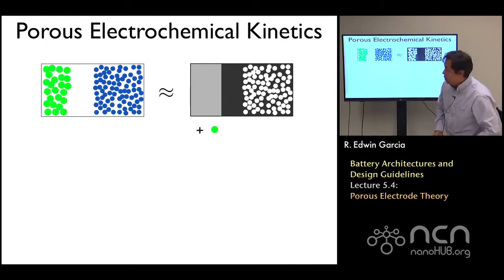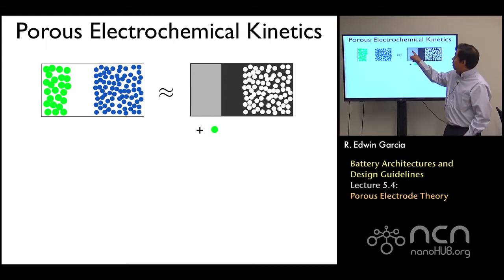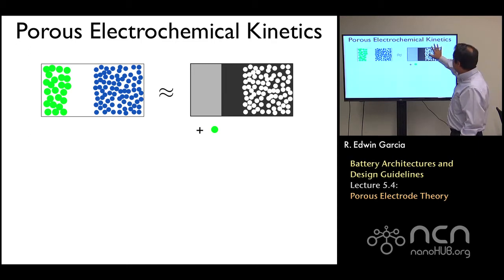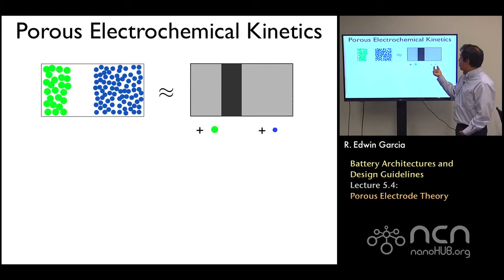And on top of that, I am going to replace all the particles inside the anode by a representative particle that allows me to describe the transport through that layer. Okay, and on the cathode side, I can do the same thing. I'm going to average out the properties of the topology associated with the cathode itself, and instead replace it by a representative particle that I can put as a test particle in every spot, just to be able to describe the lithium accumulation